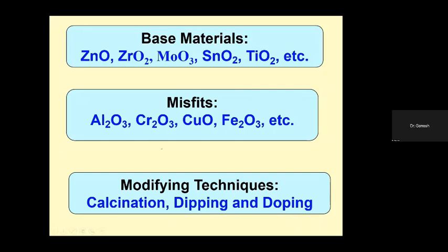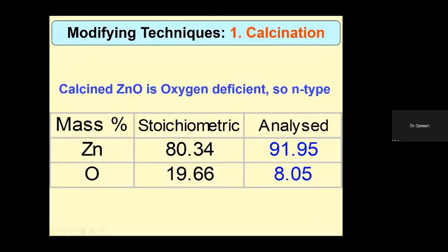So these are the low cost techniques, again, to modify the gas sensors or to modify the sensing performance of different materials. The first modifying technique is calcination. If the material is calcined at high temperature, taking the example of ZnO, above 500 degrees Celsius it liberates its oxygen. Oxygen is removed and the material gets oxygen deficient.